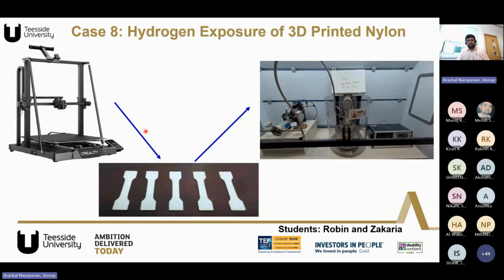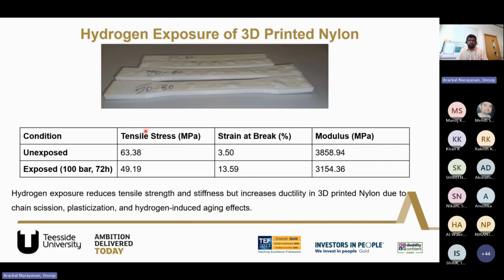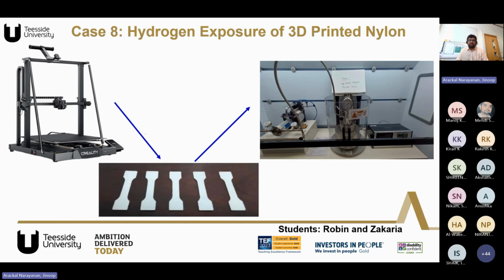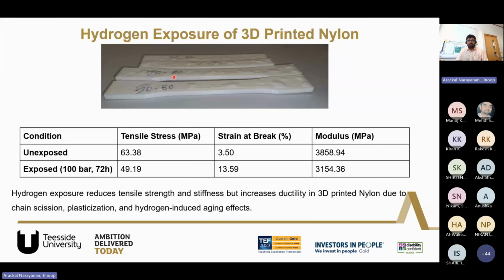And one of the recent works that we did as part of a UK Iceland project is exposing hydrogen to a 3D printed nylon part. So we 3D printed nylon, and then we used our facility, Net Zero Center, to expose the material to hydrogen conditions. In this case, I think we used 100 bar and 72 hours for exposure, and you could see how the samples have become after hydrogen exposure. We could see the bubbles, we could see the hydrogen trapped in the material, and we could see reduction in the mechanical strength and the modulus after hydrogen exposure.